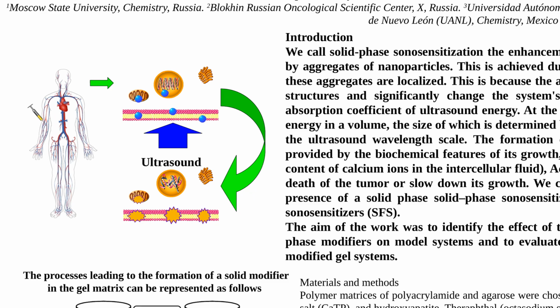The aggregates differ in their physicochemical properties from the surrounding biopolymer structures and therefore significantly change the response of the system to ultrasound exposure. They locally increase the absorption of ultrasound energy. At the same time, solid phase modifiers can localize acoustic energy within a volume determined by the size of the aggregates. This volume can be significantly smaller than the wavelength of the ultrasound.